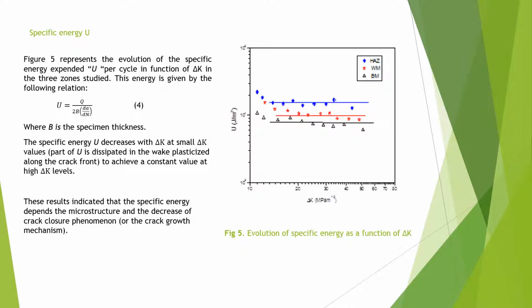Part of U is dissipated in the wake plasticity along the crack fronts, to achieve a constant value at high delta K levels. These results indicated that the specific energy depends on the microstructure and the decrease of crack closure phenomena.